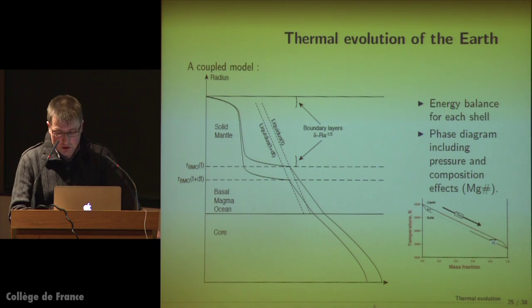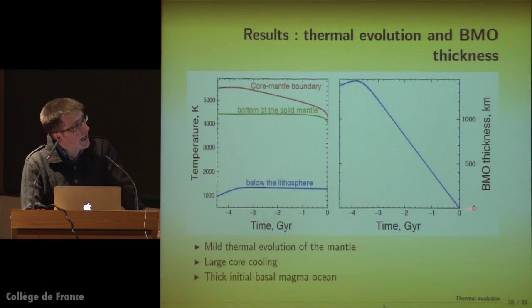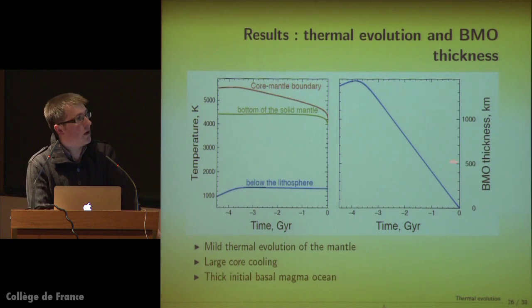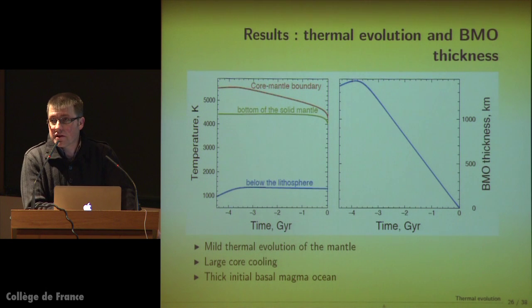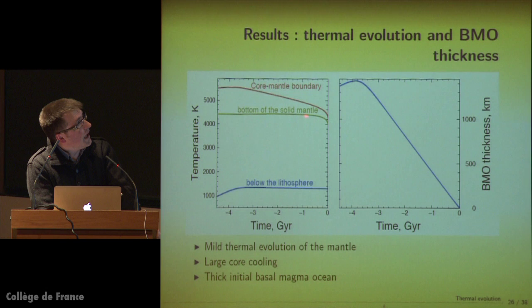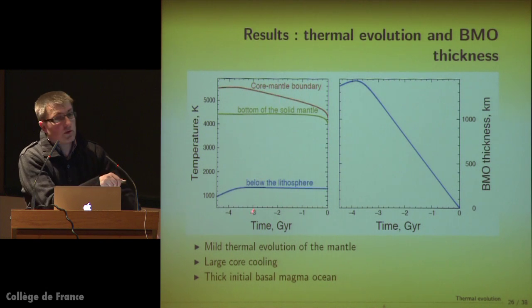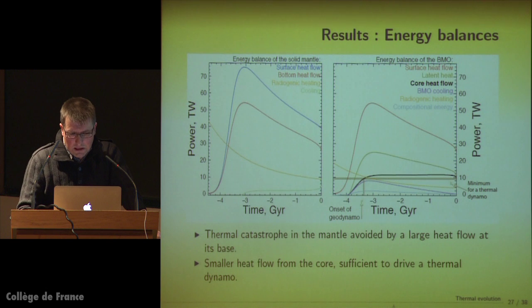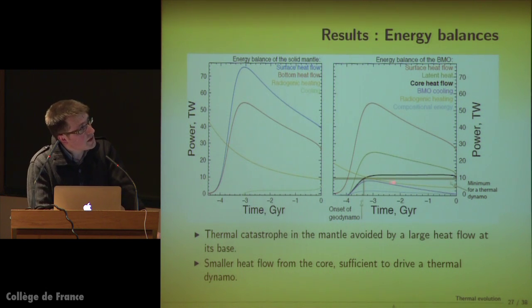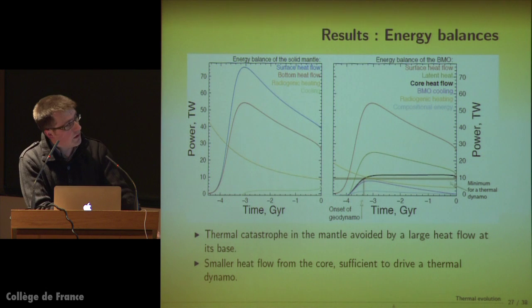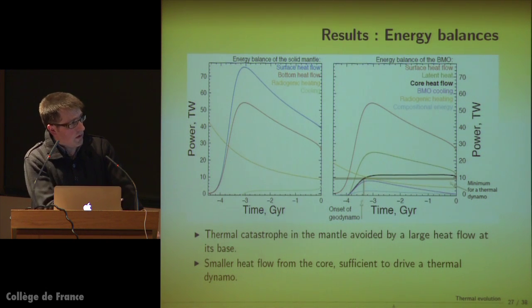And this is coupled to the basal magma ocean and the core. And so with that, starting from an almost zero thickness of melt, now we go back to something like a 1,000 kilometer thick basal magma ocean in the early Earth. And we do that with heat flow at the surface, which is almost constant, while the heat flow at the bottom of the solid mantle and the heat flow at the core mantle boundary changes much more with time. And these are the different energy terms in the balances. The key thing to look at here is that the heat flow at the core mantle boundary is here, and is actually over the minimum value for dynamo, barely above, so it's not very satisfying, but still we can make a dynamo run for 3.5 billion years.